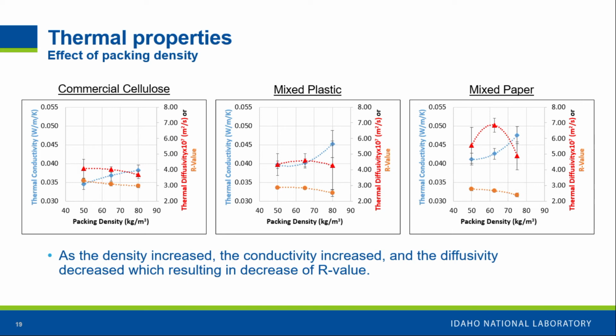This figure is telling how the packing density of each material affects the thermal properties. You can see that with the increase of the packing density, we are increasing the thermal conductivity, which makes sense because when we increase the packing density, the particles come close together. So when they are in contact, they can transfer heat better. That means it works as a more conductive material. When we increase the conductivity, obviously it will oppositely affect the diffusivity as well as the R value, as those are inversely proportional.